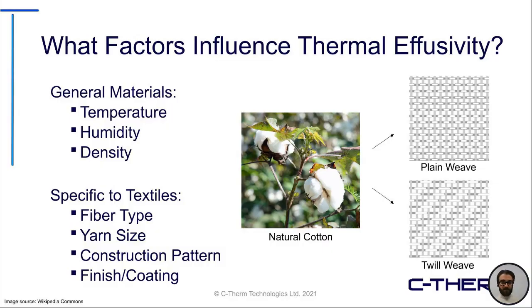Coming back to textiles and what factors really influence your thermal effusivity. Talking about general materials, really temperature and humidity. Those are two environmental factors that will be very important to control for, but also to take note of during your testing. Generally speaking, they will influence the thermal properties of any material. Some are more sensitive than others, but temperature and humidity should be controlled. And if you are looking to test specifically according to the ASTM D7984 standard, there are guidelines in there on the acceptable ranges for those two parameters.